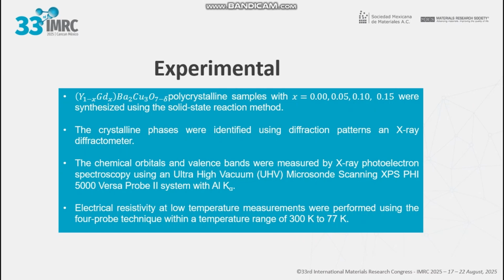So to do this, we synthesized yttrium barium copper oxide doped with gadolinium polycrystalline samples for the concentrations of 0, 0.05, 0.10, 0.15 using the solid state reaction method. Then we characterized the compounds using an X-ray diffractometer, and we identified the crystalline phases. Later on, the chemical orbitals and valence bands were measured by X-ray photoelectron spectroscopy using an ultra-high vacuum microzone scanning with the specification shown here. And lastly, we characterized the samples by their electrical resistivity at low temperature, with measurements performed using the 4-probe method within a temperature range of 300 Kelvin to 77 Kelvin.